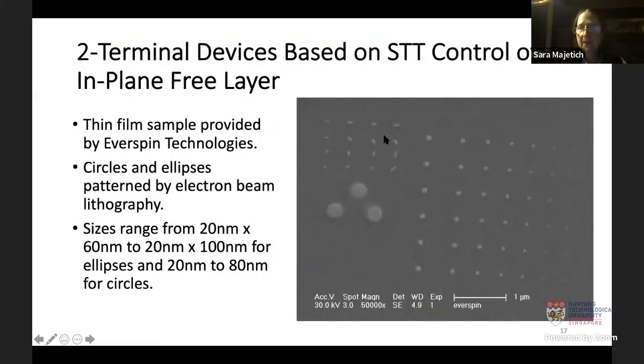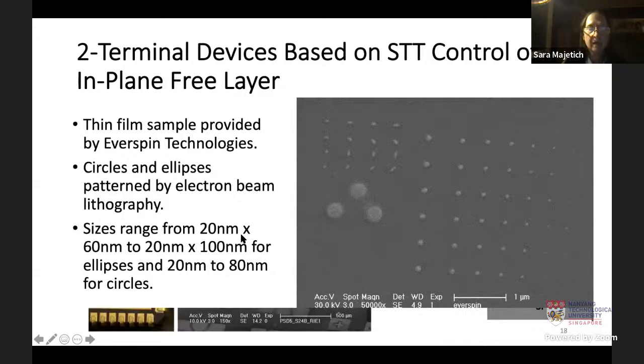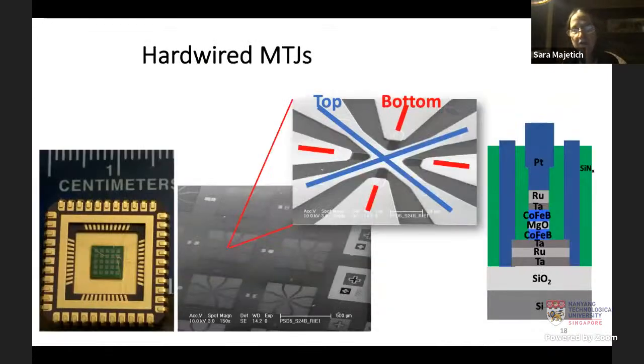Here's an SEM image of different pillar devices, dots of different sizes, ellipses, different angles of the ellipses. So we can make these of different kinds of MTJ geometries. But of course, if you want to put them together, you need to hardwire them, and so that makes the nanofab a lot more complicated. But we can do that, and we can make little chips in chip carriers that have lots of individual devices and wire bond them, and so we can connect them to each other.